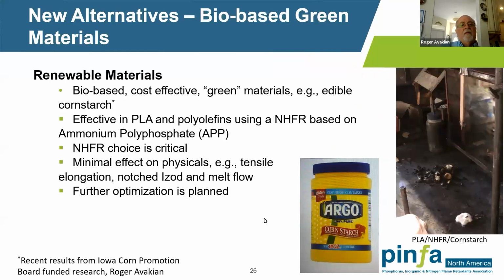Indeed, the material here is a bio-based green material, for instance cornstarch. It's a bio-based, cost-effective green material. It's the material that was used in my studies, and you can see the diagram to the right here, which is PLA and a non-halogen flame retardant based on ammonium polyphosphate, and then cornstarch. And indeed, this is the cornstarch. You can go to Walmart and buy this stuff and use it as is. So it was nice, as it's readily available, commercial, and fairly low cost.